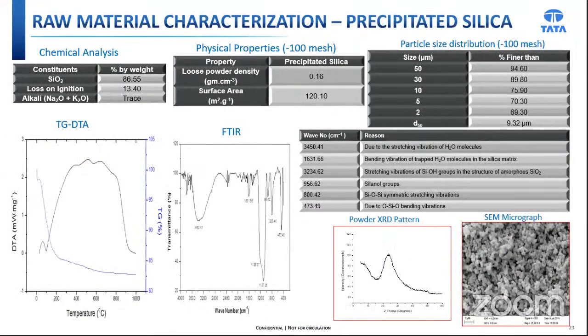The precipitated silica has a silica percentage of 86.55%. It is purely amorphous in nature. The powder XRD pattern indicates the material is almost amorphous. The SEM study illustrates that the amorphous silica particles have almost uniform size distribution, varying from 50 to 70 nanometers. These primary particles have the tendency to agglomerate, leading to large particle size.